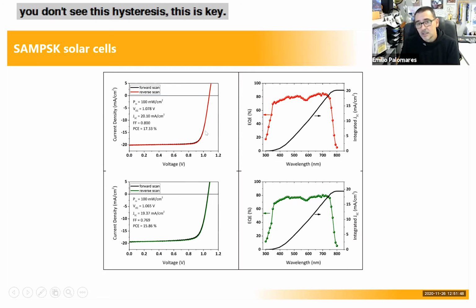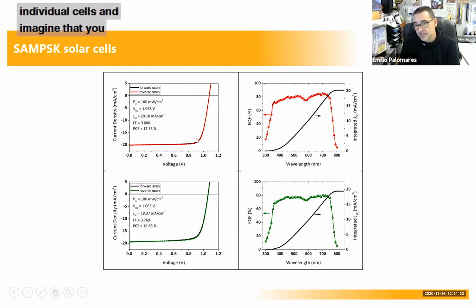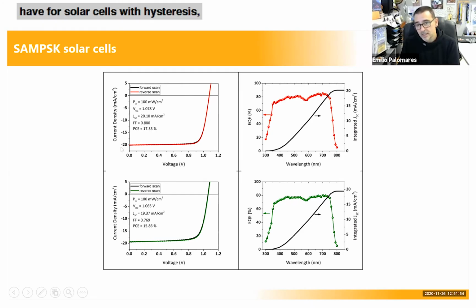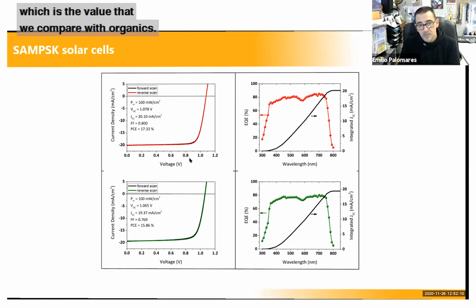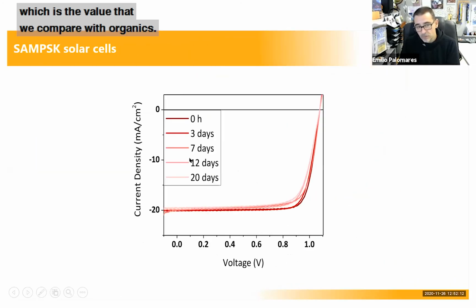This is key if you want to make modules, because modules are made of individual cells. And imagine that you have solar cells with hysteresis, your module will be very bad. So SAMs helps you to reduce the hysteresis quite a lot. In fact, I would call this hysteresis free. And as you can see, efficiencies are well above the 15%, which is the value that we compare with organics.